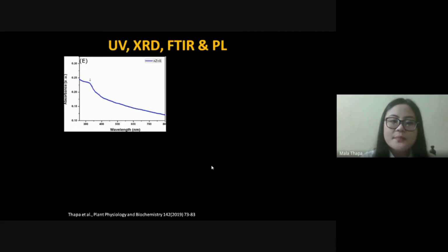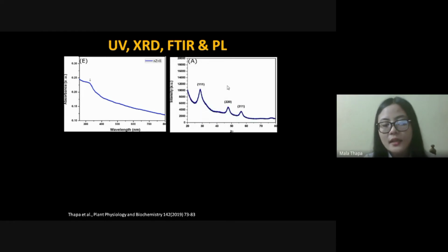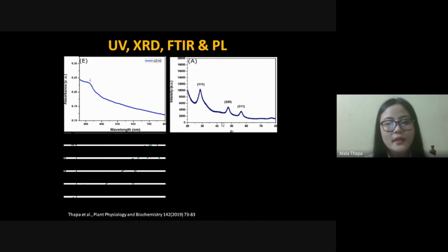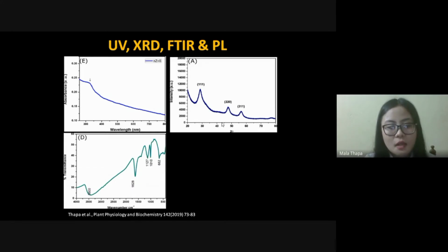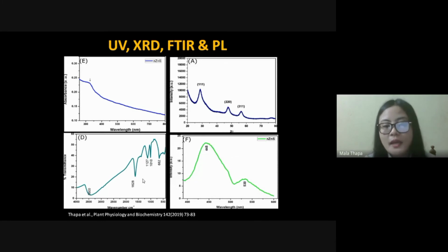This is an image of UV spectroscopy. This is showing the characteristic hump-shaped curve for synthesized zinc sulfide nanoparticle, and confirmed that the synthesis of zinc sulfide nanoparticle was successful. This is a XRD image of synthesized nanoparticle, and these are the characteristics of synthesized zinc sulfide nanoparticle. Now this is a FTIR image which shows the surface functional group of synthesized zinc sulfide nanoparticle. And finally, this is PL spectroscopy image of synthesized nanoparticle, and confirmed that the synthesized nanoparticle was zinc sulfide nanoparticle, because these are the characteristic for zinc sulfide nanoparticle.